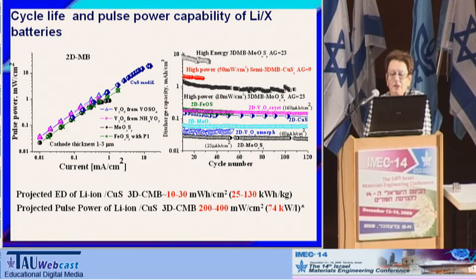centimeter, and peak pulse power of this semi-three-dimensional cell was about 50 milliwatt per square centimeter. This is 5 times that of the full three-dimensional cell with molybdenum oxysulfide cathode fabricated on the substrate with area gain 23. We expect that the energy density of lithium-ion copper sulfide battery, I mean full three-dimensional concentric microbattery,